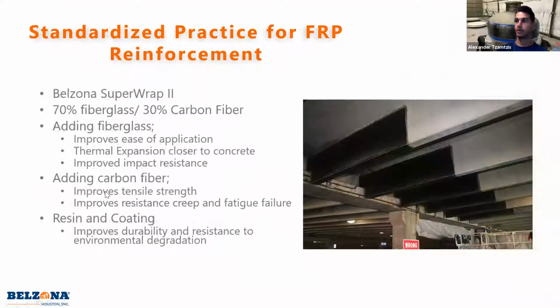So the Belzona Super Wrap 2, it's a 70% fiberglass, 30% carbon fiber reinforcement. We have 100% solid Novolac epoxy that we mix with the reinforcement. Once you mix it into the reinforcement, you can mold it around whatever structure you need to mold it around. And then once it cures, it forms a hard composite. So there's different reasons why we have the 70 and 30% fiber, the ratio of fiberglass to carbon fiber. Generally, adding the fiberglass makes it a little more pliable, so it's a little easier to work with. Your thermal expansion is going to be closer to steel and concrete. Carbon fiber doesn't have much thermal expansion, so adding the fiberglass, you can match the thermal expansion better to concrete.